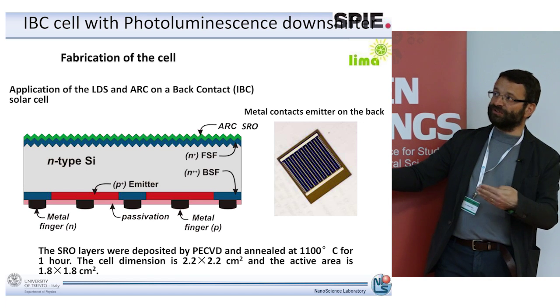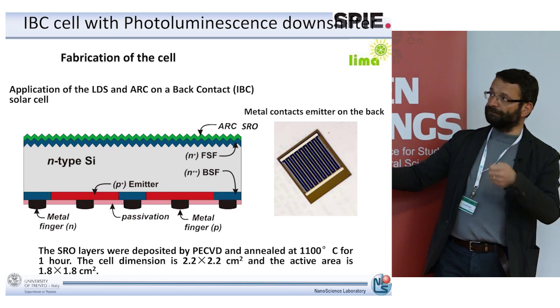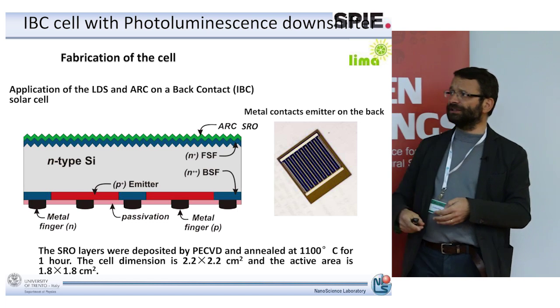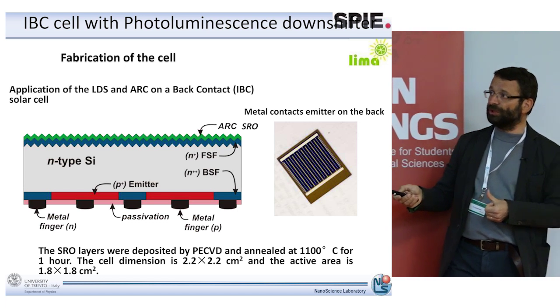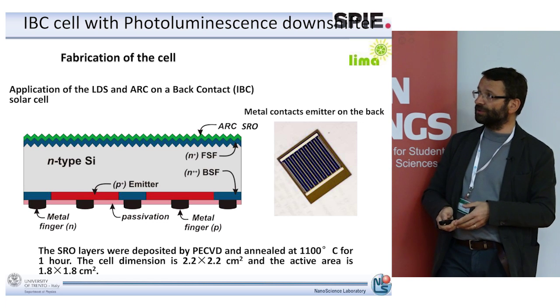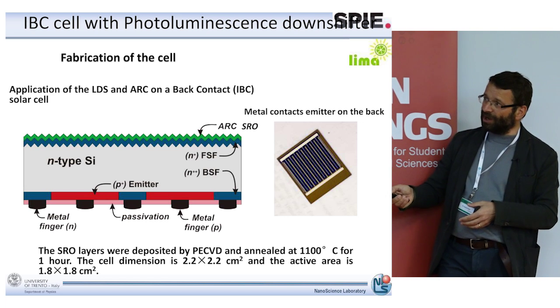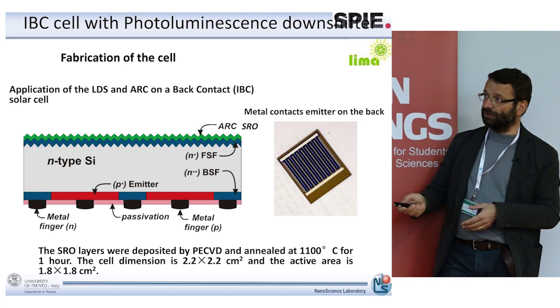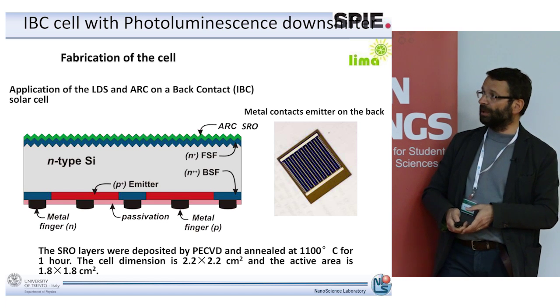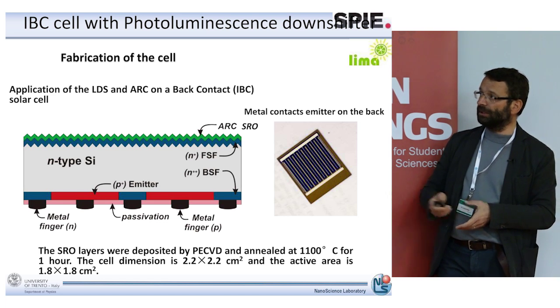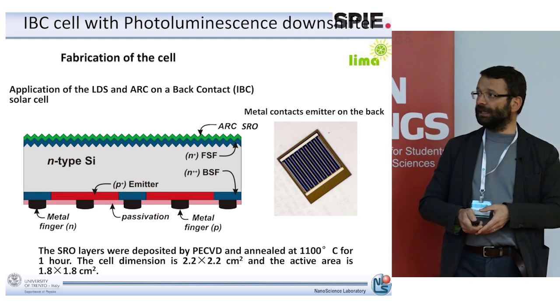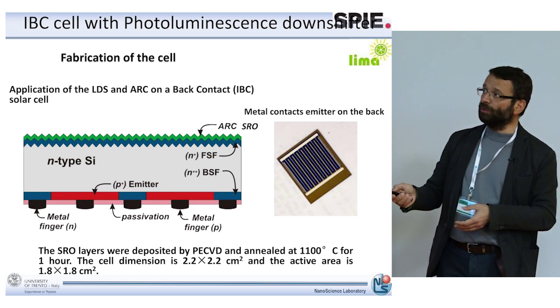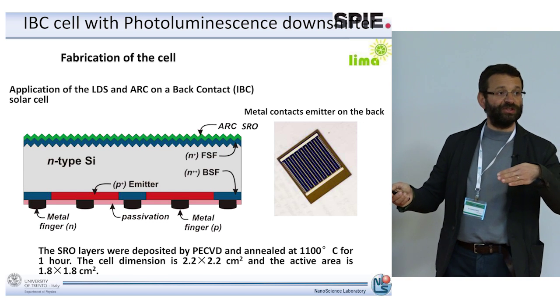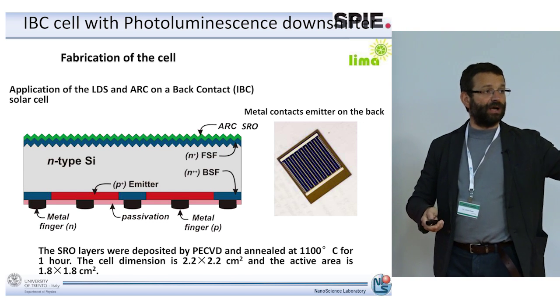On the front of the cell you have only a texturing in order to trap the light, to reduce the reflection from the cell, but all the contacts are on the back, so no shadowing from the top, from the metal lines on the solar cell. This one is a state-of-the-art solar cell in production, and what we did was to put on top of this cell a layer of silicon nanocrystals.